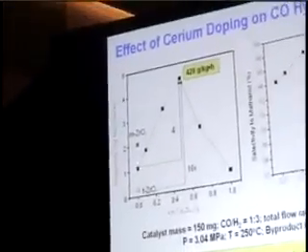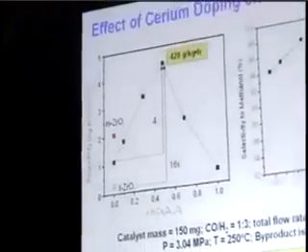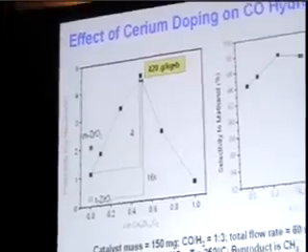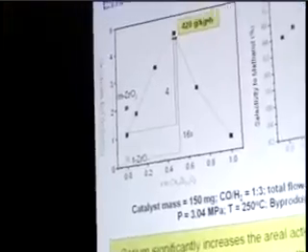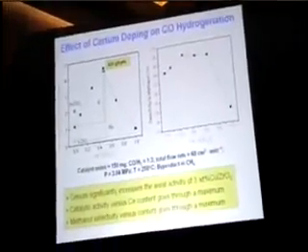Remember, this is a kind of a hybrid, and pure monoclinic is here. So you do even better than the pure monoclinic. And if you take your worst catalyst relative to your best, you've gone uphill by a factor of 16. And for people who have an industrial bent, the unit of merit here is grams of methanol per kilogram of catalyst per hour. And in those units, this most active catalyst is 420, which puts it in the high end of performance of commercial methanol synthesis catalysts.